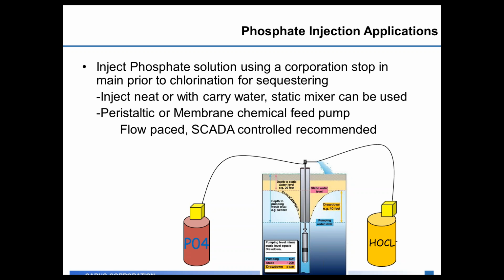In a surface water plant, you're obviously going to do, in most cases, oxidation, coagulation, filtration. The phosphate's going to be added at the back of the plant, usually after filtration, as one of your final chemicals to the treatment process. Phosphates can be fed neat directly out of the container or the bulk tank. You could use carry water if you need to, and you could have a static mixer in the line, but phosphates blend in with the water very rapidly.